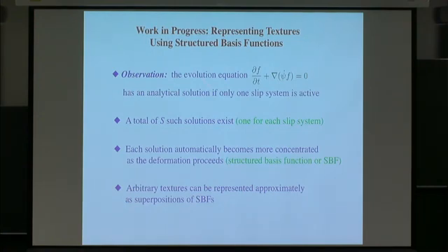So we have this evolution equation here, and it turns out that that equation has an analytical solution, somewhat complicated, but nevertheless analytical, in the limiting case when only one slip system is active in the aggregate. However, there are a total of S such solutions, one for each slip system. And the advantage of these functions is that each solution automatically becomes more concentrated as the deformation proceeds. And that's why I call them a structured basis function, or an SBF, because they grow with the deformation.